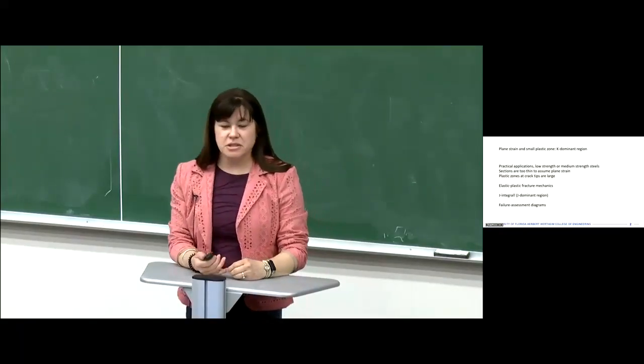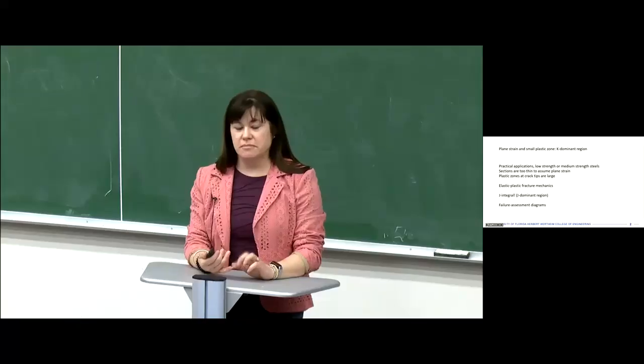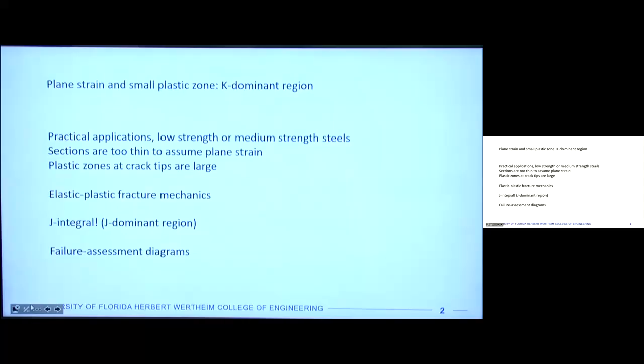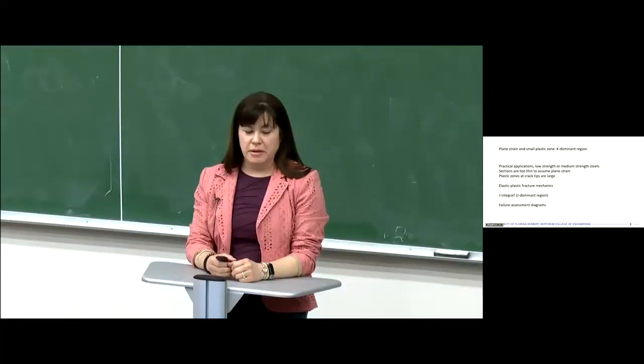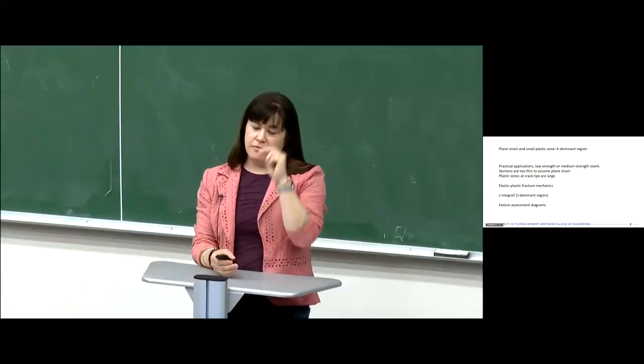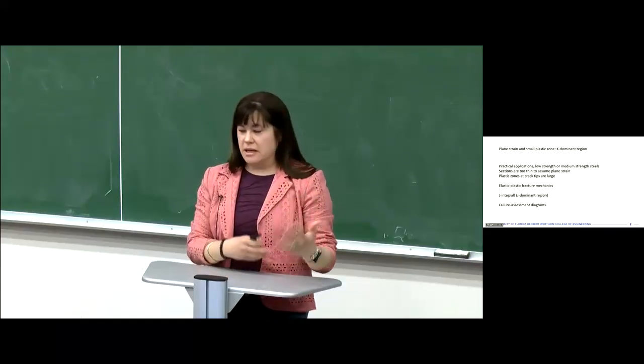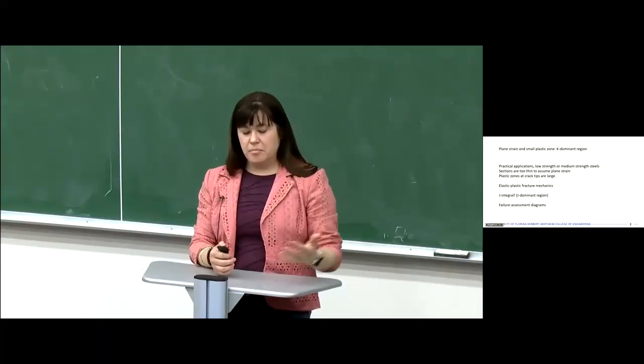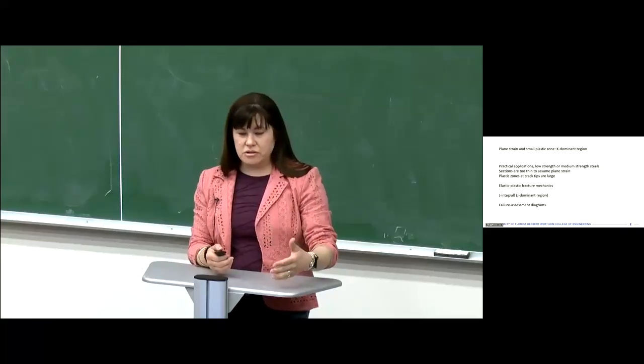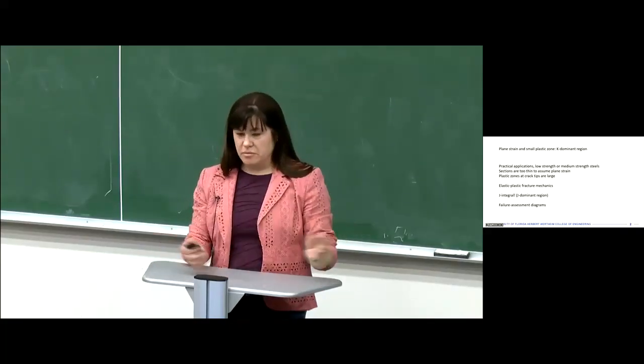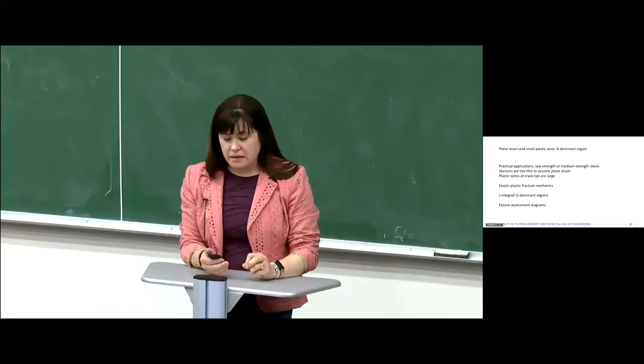So we had to make some assumptions. The first one was that we're in a plane strain regime, which means we have a relatively thick component that allowed us to make some assumptions about the stresses in the crack tip. And we assumed we had a very small plastic zone, so that when we were pulling on a specimen, sort of far away, we don't have to worry about plastic deformation. We can assume the whole thing is elastic except for right at the crack tip. And we just kind of say that if stresses go above the critical fracture toughness, we would expect failure. And so that is good.